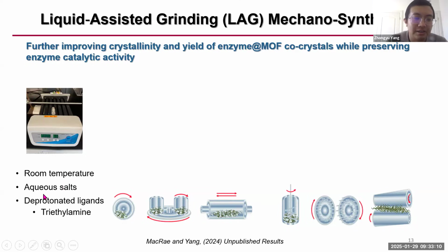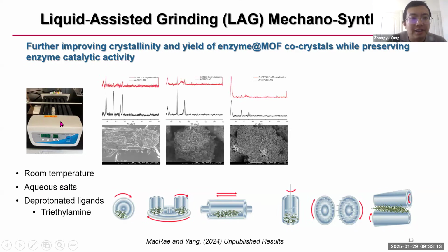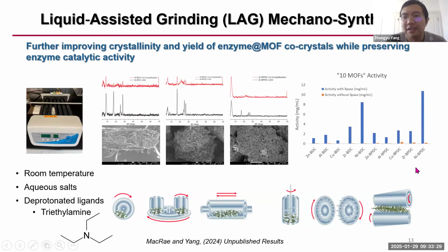Everything is room temperature. It's aqueous, but we put some salt, and then we did see a significant improvement in some of the multi-phase or amorphous morphs. You can tell in the black data, there are sharper peaks, and all of the enzymes are active in this liquid-assisted grinding synthesis. We're running simulations, and hopefully we can have that paper out. So this is the first application. We use co-crystallization to trap enzymes during the morph formation.